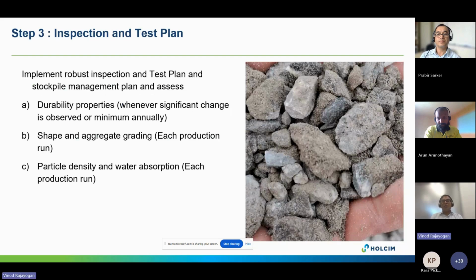In addition to that, we also monitor all the durability properties in line with the standards, and it's regularly assessed for Los Angeles abrasion, wet-dry strength variation, ASR, and weak particles. In each production run, we also check for shape and grading, particle density, and water absorption to ensure what and how this product can be used.